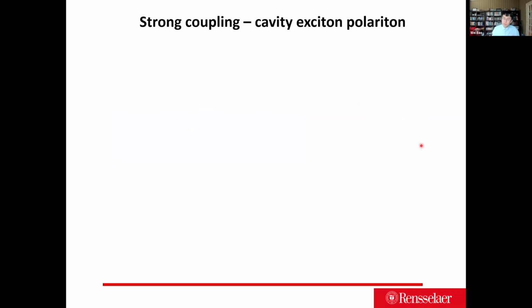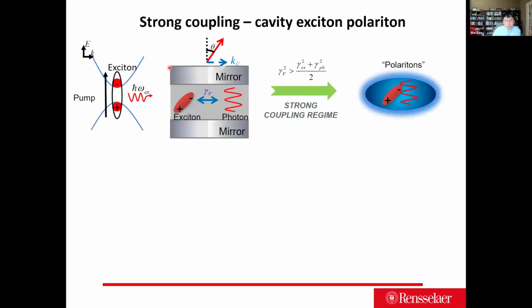So one of the subfields gradually emerged because of this thought, which is to couple two boson systems together, the so-called cavity exciton-polariton. The basic idea is that we have a semiconductor that possesses excitons. Essentially, an exciton is an electron-hole pair residing at the band edge. When you excite them with a laser, you create an excitation in this semiconductor. If you also have a cavity, you will also trap photons. The typical cavity we use in the field is the Fabry-Pérot cavity, essentially two flat mirrors.